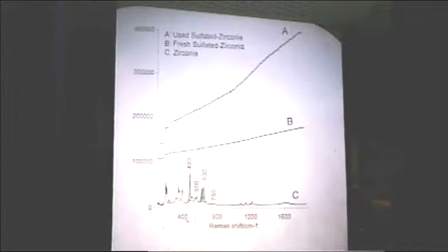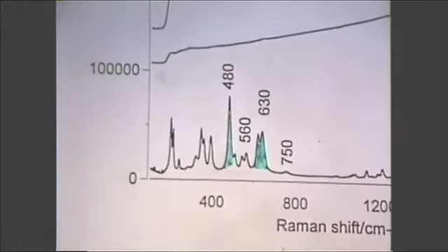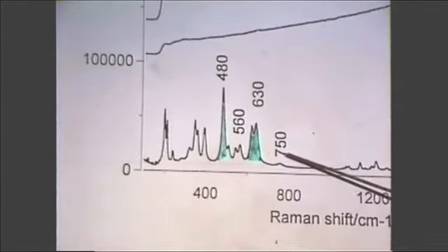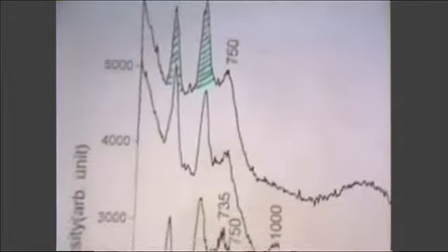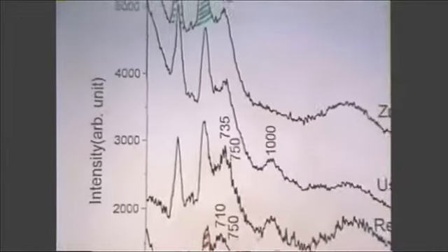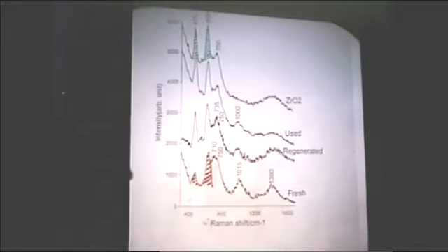It's surprising in a way because if you just look at zirconia itself without the sulfate groups, then you get a very nice Raman spectrum. And this is what we get from a sample of zirconia. This pattern of peaks is representative of the so-called monoclinic form of zirconia, which is the stable form of zirconia at low temperatures. Okay, so we went ahead and measured the Raman spectrum using the UV excitation for the sulfated zirconia, and the result we get is summarized in this transparency.